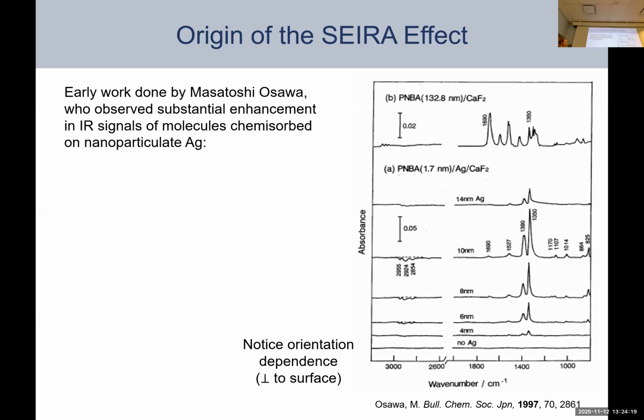So this is the signal enhancement aspect, but not too large, because now you peak and you sort of decay in terms of signal. Okay, so I wanted to also draw your attention to the fact that the relative intensities are very different in these SEIRAS spectra down at the bottom compared to just para-nitrobenzoic acid that has no orientation specificity. So here you can see actually it's this 1690 wavenumber peak that's highest, most intense. However, on a surface, it's the 1350 wavenumber peak that's most intense, okay?